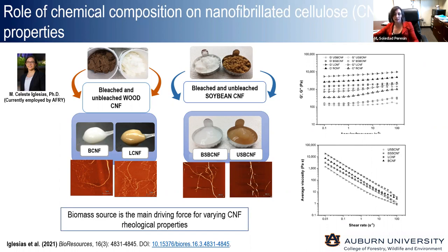For this, what she did was a sequential delignification of the fibers and tried to understand the flow behavior of this material and how this was correlated to the morphology of the fibers. And she also compared wood base source with soybean nanofibrillated cellulose, also completely bleached and lignin containing. And she was able to work on a very nice fundamental piece of work that elaborates on these rheological properties and how the structure of the fibers are mainly driven by their chemical composition, and also how that affects the final rheological behavior of these.